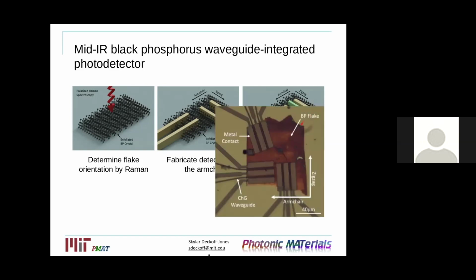So here is an optical microscope image of one of the actual fabricated devices. We have a number of different devices here. There's actually 6 devices where these are the metal contacts, and then in between them, these are the waveguides. And so on this particular flake, we're comparing this waveguide with this waveguide along the armchair and zigzag directions. I forgot to note that also, because of black phosphorus's reactivity, so that we could measure the devices over a longer period of time, in addition to the waveguides, we also deposited a thin 30 nanometer layer of chalcogenide glass over the entire sample to improve the lifetime of the devices so that they didn't degrade too quickly.